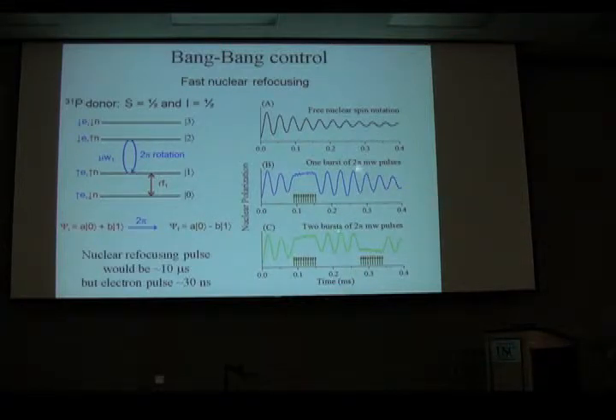And just for testing it, what we did was, well, let's just drive the nucleus with RF. Let's just do Rabi oscillations on the nucleus. And then we can put in a burst of these microwave pulses and we can essentially just freeze the nuclear spin wherever we want it. So here we send in one burst of microwave pulses on the electron and it just stays there. And then when we're done, it continues on its way. Or we can come down here and here we send in one burst and then another burst and we just sort of freeze it in a position and then we let it continue on its way.